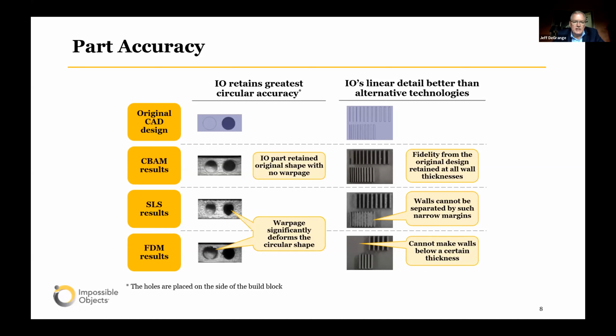So starting on the left side here and working your way down, if you look at some of the test articles we made to date and look at concentricity of holes, you can see with the CBAM results that we actually have a pretty good, nice round hole on the side of the parts. When you contrast that to laser sintering and fused deposition modeling, you start to lose your circular shape with those technologies.